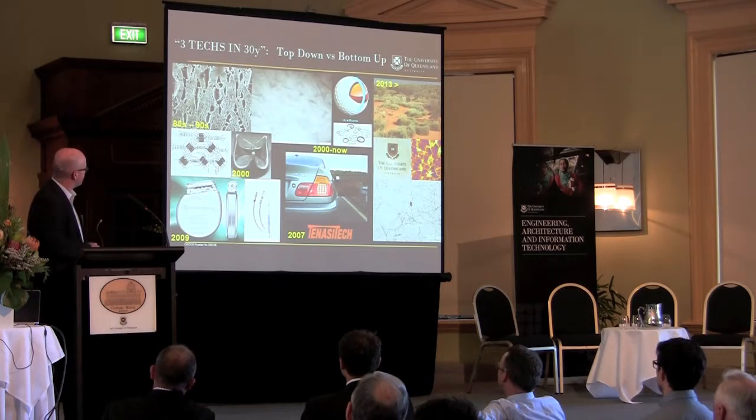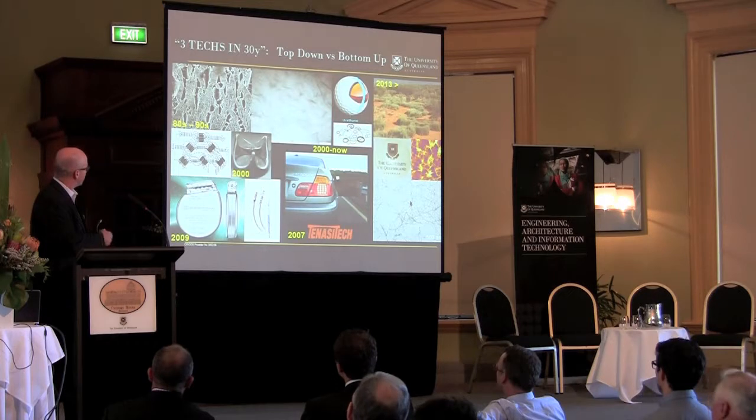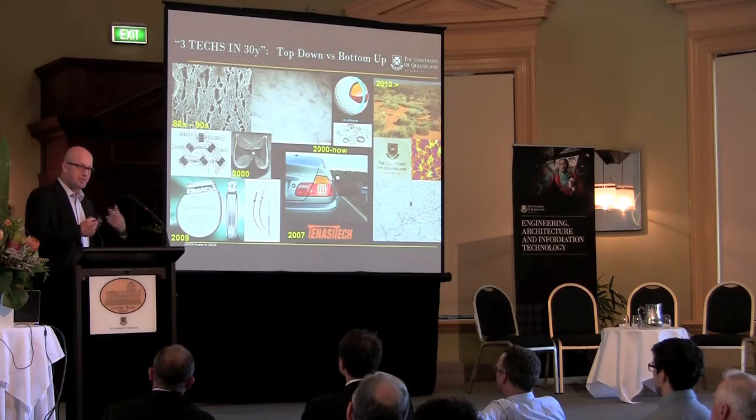So your insulation for your pacemaker leads, this is a polyurethane, actually not too dissimilar to what they use on the cover of golf balls today. But that's what they were using. And if you combine the physiological environment with a little bit of stress, whether that's a ligature site or whether that's a little bit of dynamic stress, you get what's called environmental stress cracking.